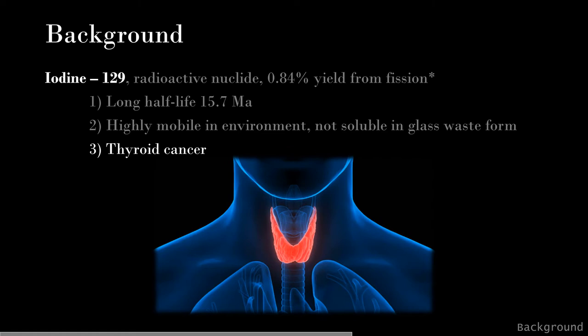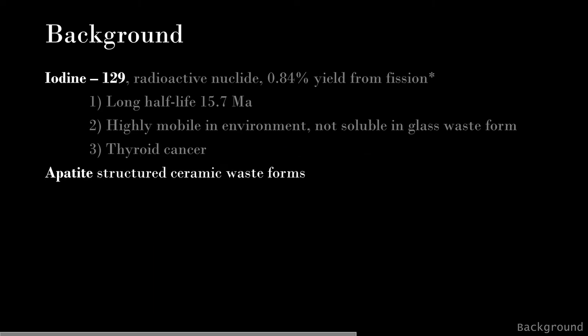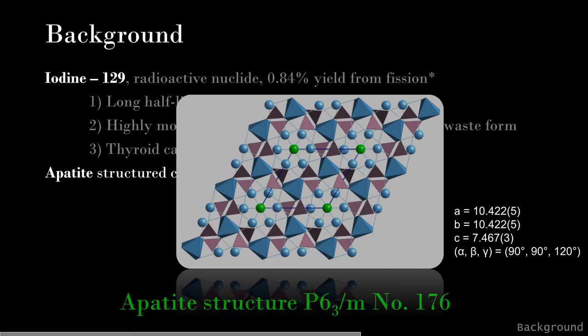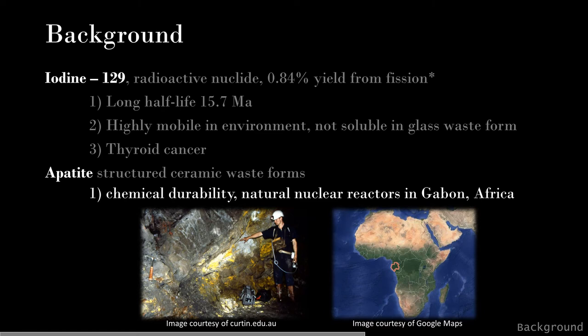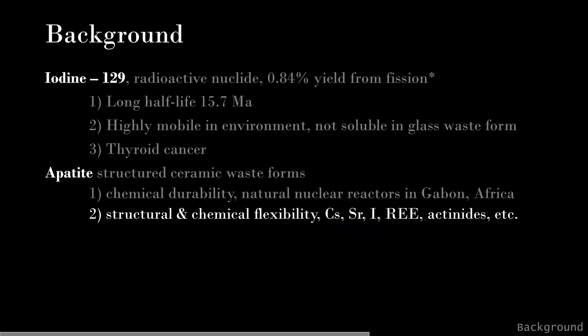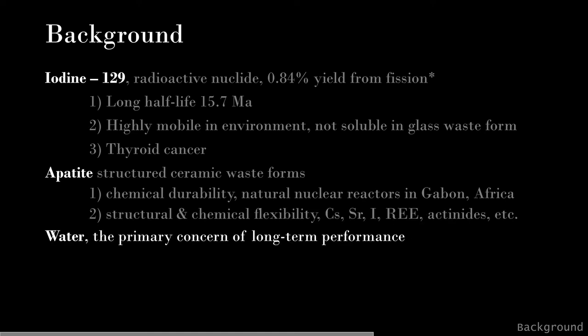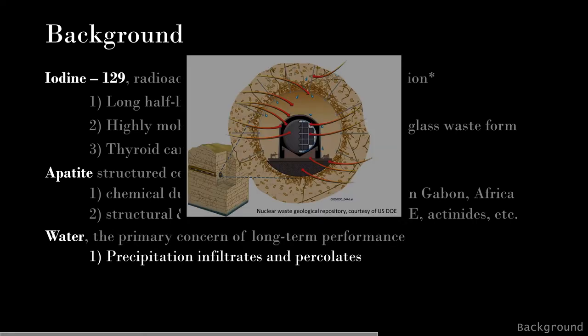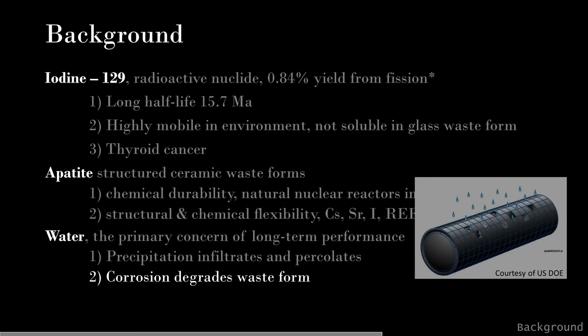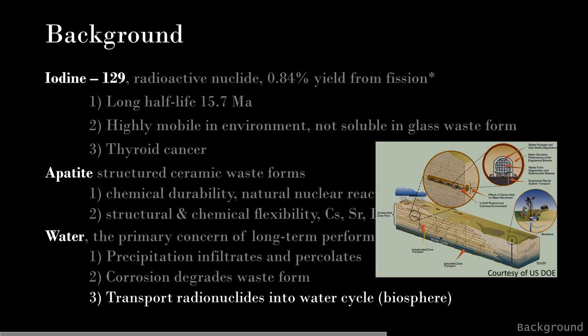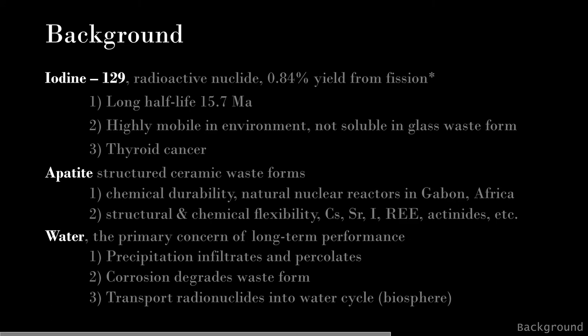We need a concrete plan to ensure the long-term disposal safety of iodine-129. Apatite structure material is a promising nuclear waste form because it is durable, as demonstrated by natural minerals and its presence in natural nuclear reactors over 2 billion years old. Apatite is also structurally and chemically flexible, accommodating a wide range of radionuclides such as cesium, strontium, iodine, rare-earth elements, and actinides. For long-term safety, water is the primary concern—it can travel underground through infiltration and percolation. In a geological repository, nuclear waste forms are packed into a metal canister; eventually water will breach the canister and degrade the waste form, transporting radionuclides through the water cycle to the biosphere.